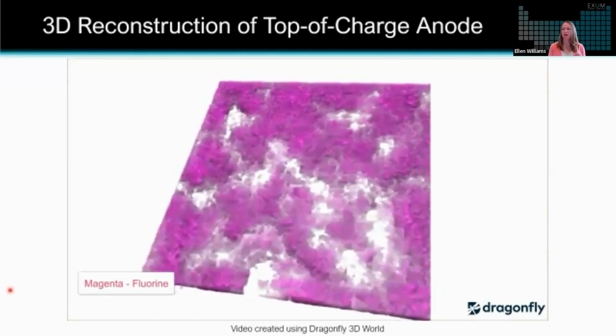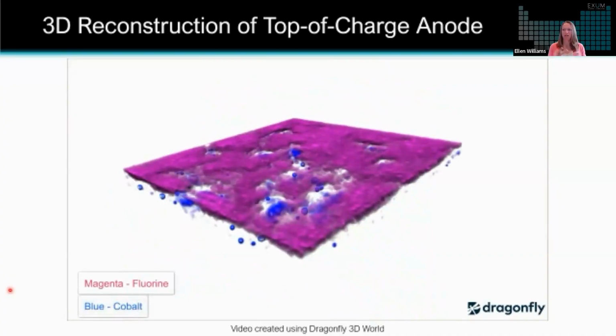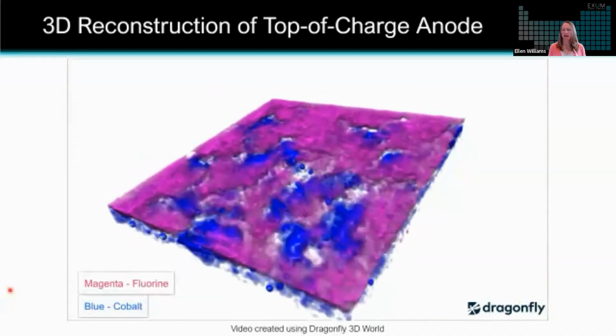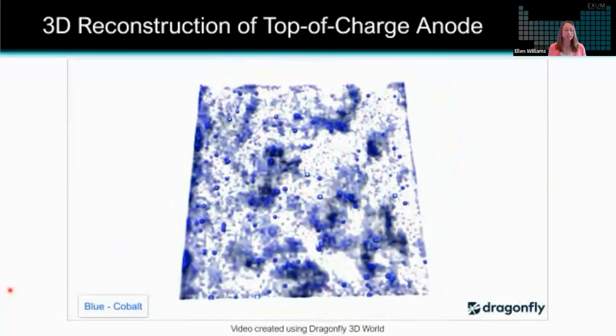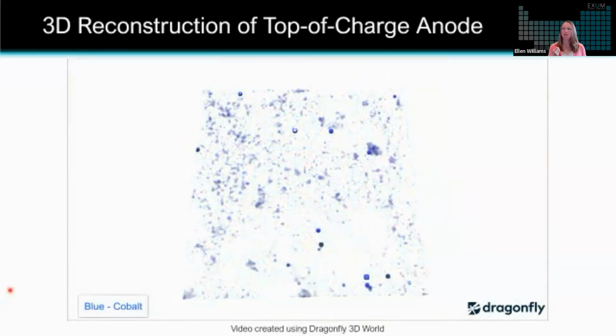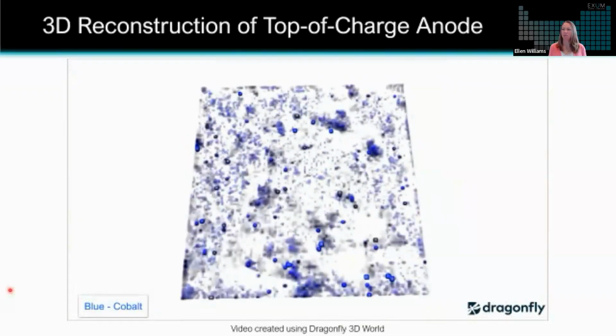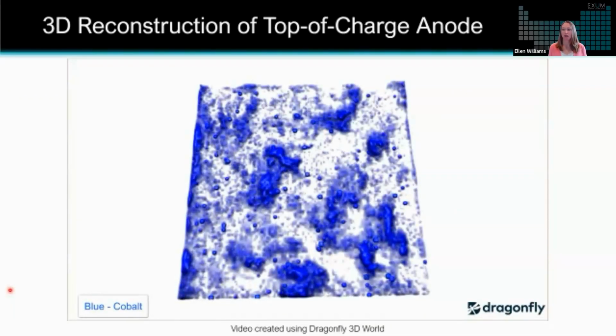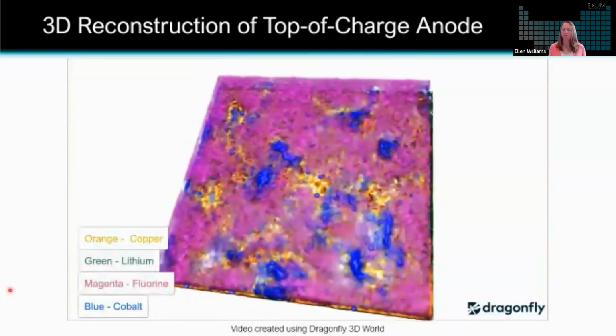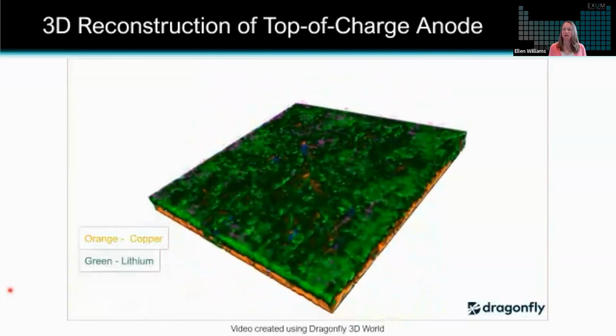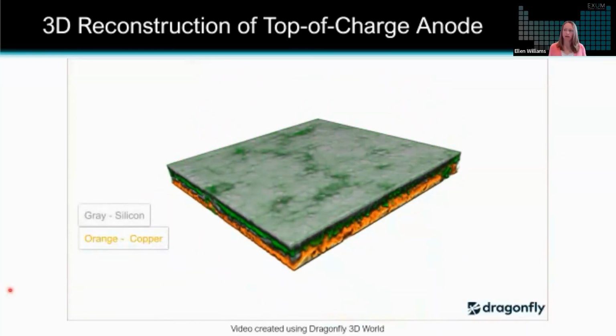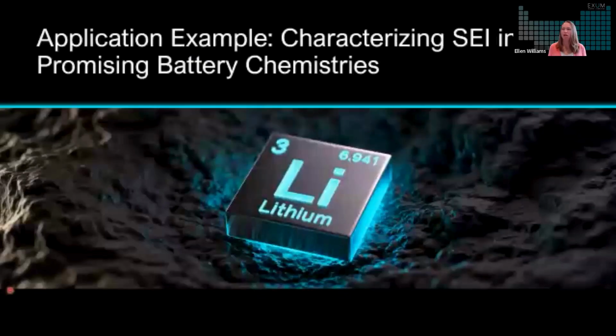We see the lithium ions, we see the fluorine that indicates the SEI, and then we can see these trace contaminants that may be impurities or may have migrated. And talking about metal migration from cathode to anode is a great segue into our final application example here, which